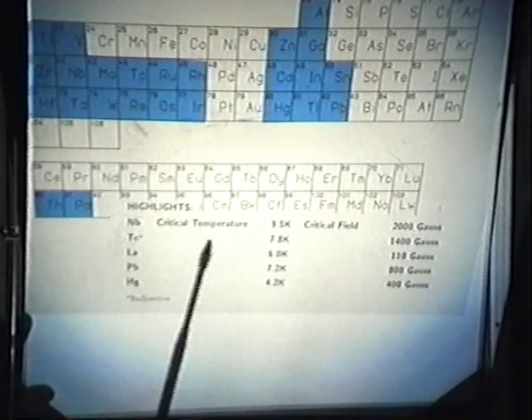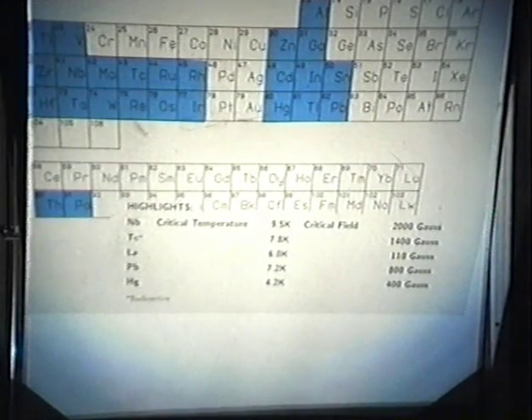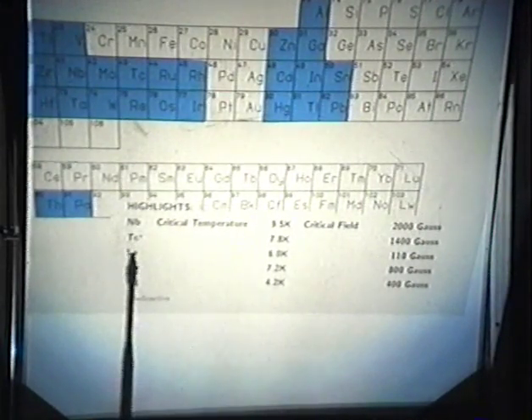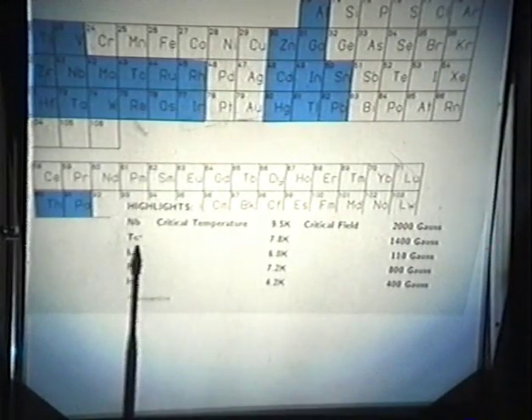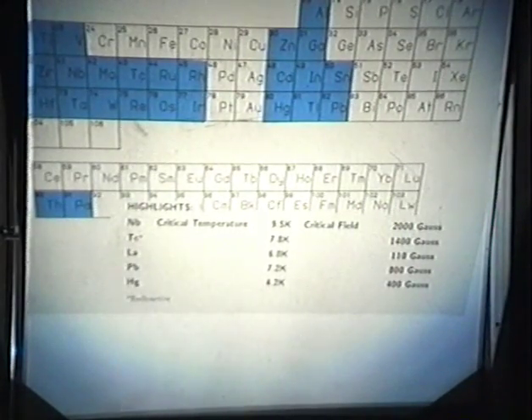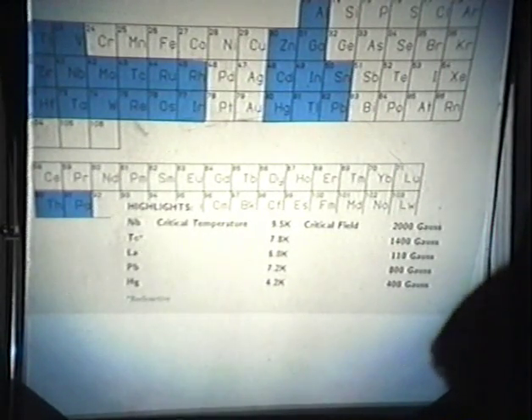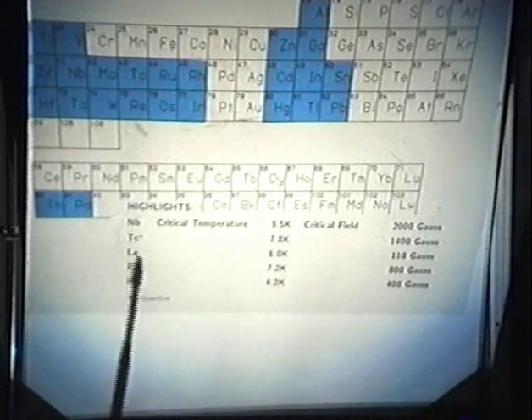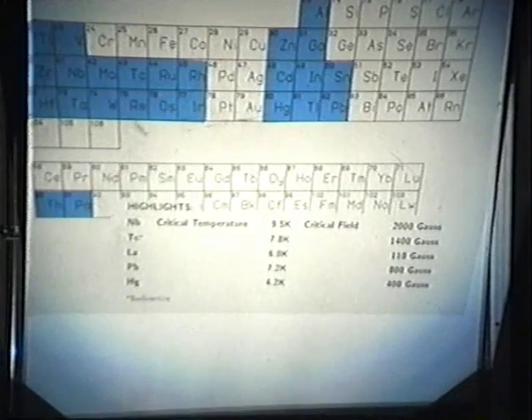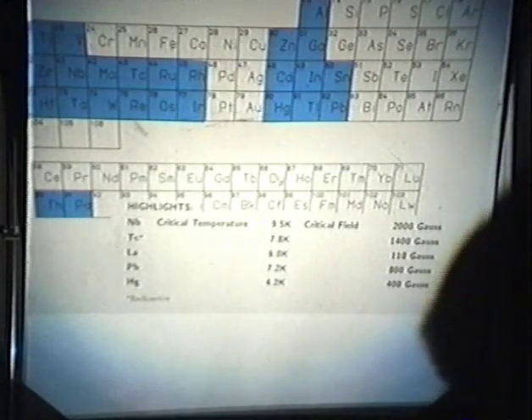Niobium metal is the best. It goes superconducting at a rather warm 9.5 degrees above absolute zero. And nature has played a little trick on us here. The next best one is technetium, which of course is a radioactive material, and there is no stable isotope of technetium in nature, so it's just a little joke here. And lead is not bad, lanthanum's not bad, mercury's not bad, and there are a few others around 6 Kelvin above absolute zero.